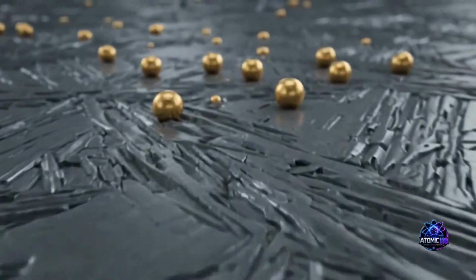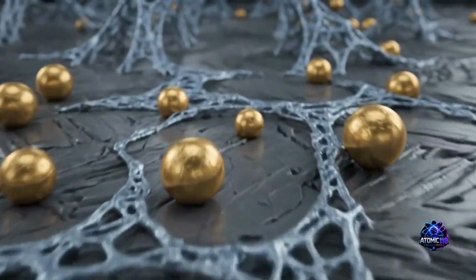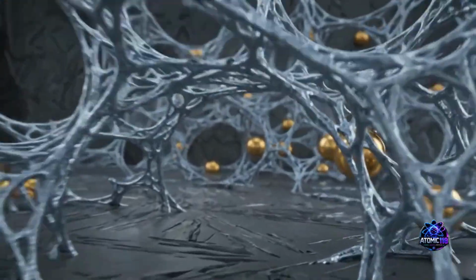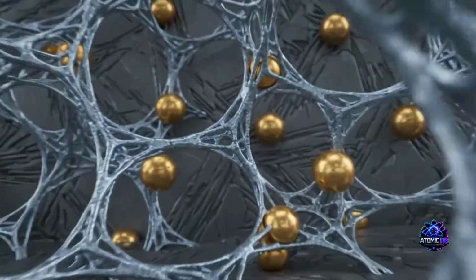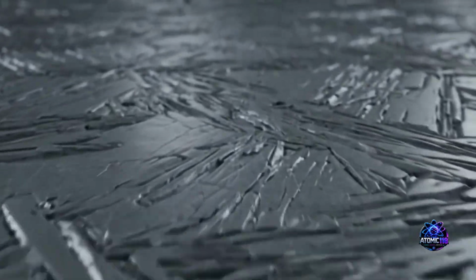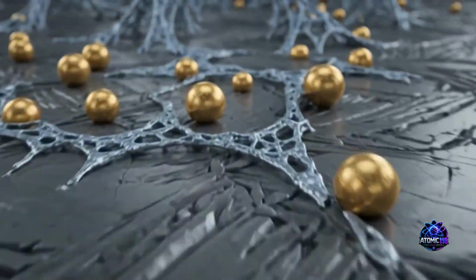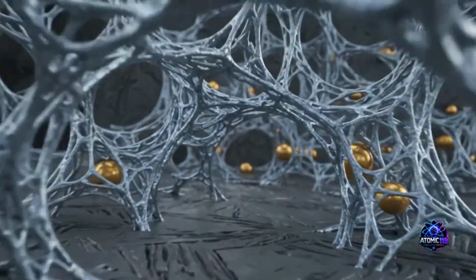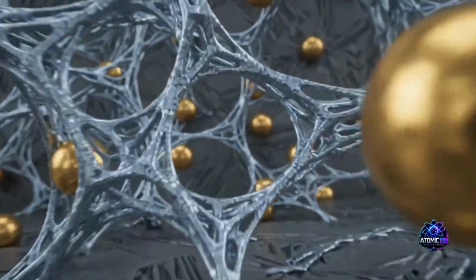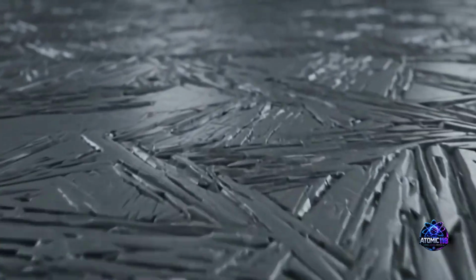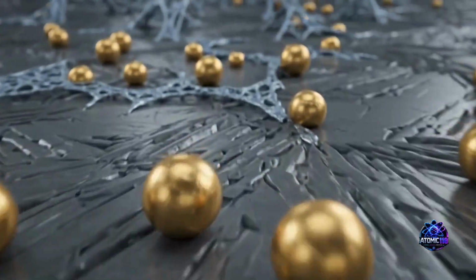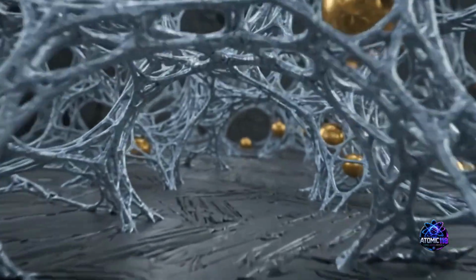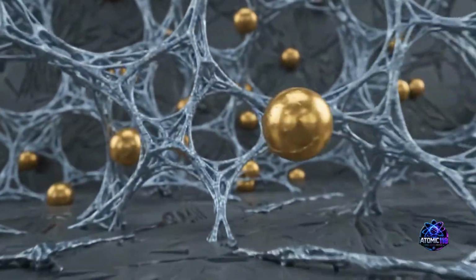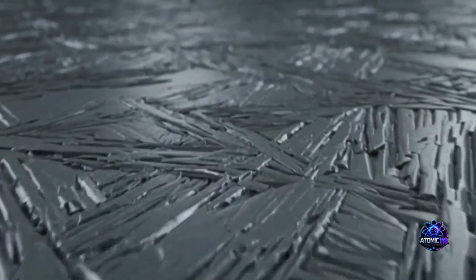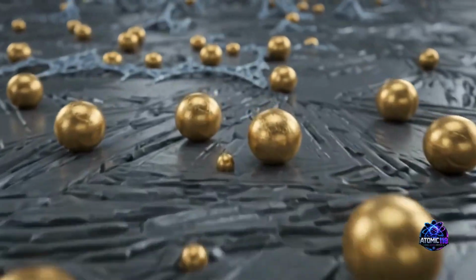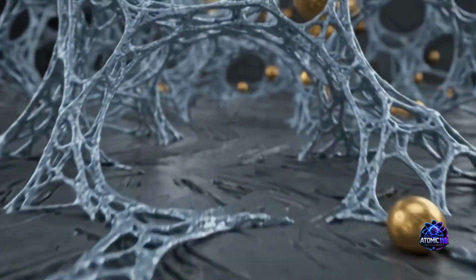But when we look at vanadium, sitting in the 3d series, the physical dynamics change entirely. Because in the 3d series, the orbitals are closer to the nucleus, right? The nucleus has a much tighter leash on those electrons. A very tight leash. The positive charge of the protons pulls those 3d orbitals inward, which physically contracts the atomic volume. And because the orbitals are pulled in so tightly, they can't reach out and overlap effectively with neighboring vanadium atoms. So if molybdenum's giving this perfect handshake, vanadium is stuck with contracted T-Rex arms.